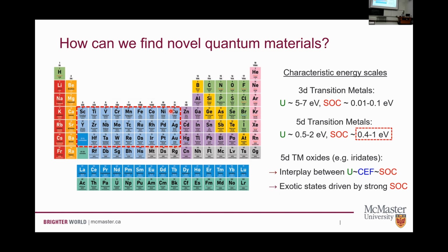So these lighter transition metals, the 3D transition metals, typically they're dominated by an energy scale set by electronic correlations. Okay, this is a big energy scale. It's about 5 to 7 electron volts. There are other energy scales set by the crystal electric field, the spin-orbit coupling. They matter, but they're relatively small in comparison.